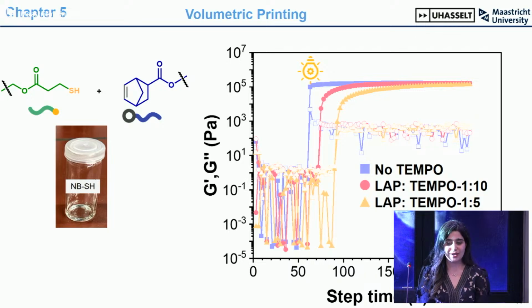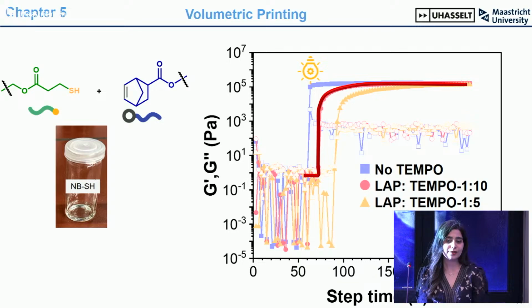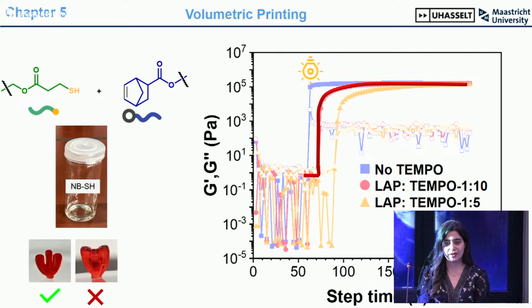The photoresin should be transparent with high viscosity. It also should have fast gelation kinetics, but also a nonlinear response to the light illumination. This is to get a clear contrast between cross-linked and uncross-linked parts, and to get better resolution. To achieve this, I use a radical scavenger, which is called TEMPO, to prolong this initial induction period. Another important parameter is the light dose, which should be precisely selected. Too much light results in overcuring and loss of detail, but too little results in weak structure.